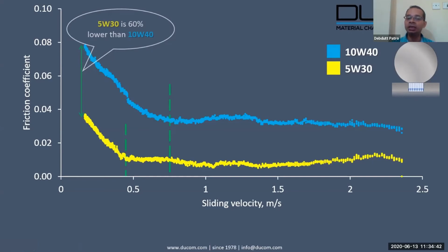So immediately it gives you an indication that going to lower viscosity engine oils is beneficial, not only in one regime of operation, but you see that the gap between these two curves is fairly consistent across this entire operating regime, which is the x-axis.